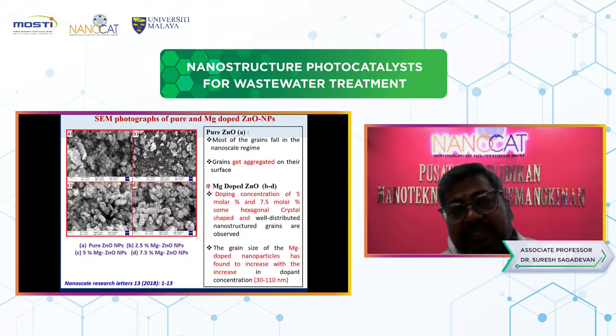And then this is the SEM image of magnesium doped zinc oxide nanoparticle. A, B, and so on are represented here. A represents pure zinc oxide, mostly grains, and the grains are already aggregated. The smaller grains are combined together to form the larger ones. In B, C, and D, you can clearly see the doping concentrations increasing, especially for the 7.5% magnesium doped zinc oxide.